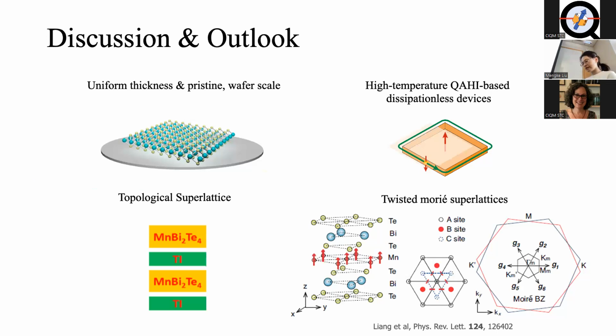I guess it's an interesting and good question. It's mostly related to whether the film can be grown. MBT, manganese bismuth telluride, can be understood as manganese telluride intercalated into bismuth telluride, right? There is a special lattice match condition between manganese telluride and bismuth telluride, and it turns out manganese telluride can have a well-ordered crystal structure, but I don't know if chromium telluride or iron telluride can. Yeah, so I think it's probably related to the lattice match condition. They can form such a well-ordered lattice. Other questions?